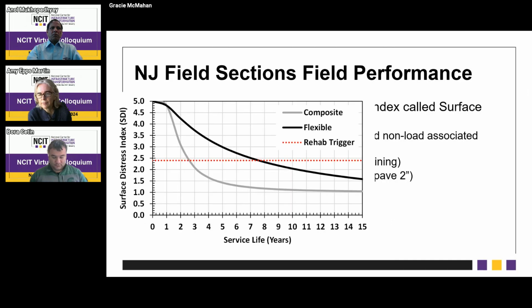Next slide, please. So on all of these, they are looking at a combined surface distress index. I'm sorry about the right-hand part of the slide. But on all of these, they monitor the surface distresses, the rutting, the cracking, all types of cracking, non-load associated, load associated, and other distresses. And they come up with a weighted single value, normalized value called surface distress index that goes from 5 for a new pavement all the way down to 0. And when it hits 2.4, that's when rehab would be considered. So that just gives you an idea of how they're monitoring the distress.